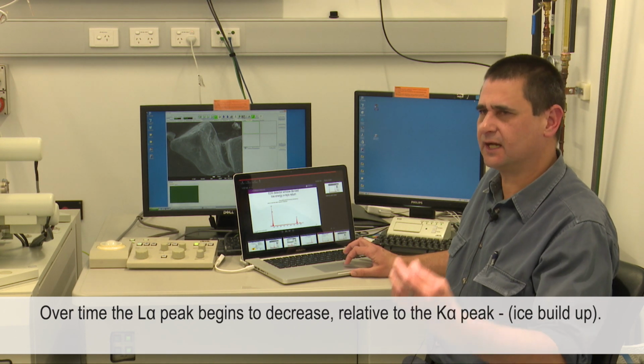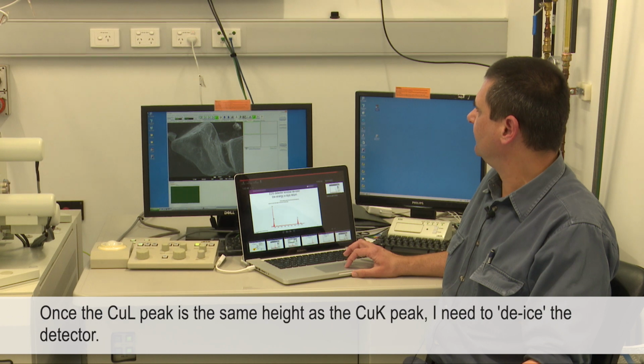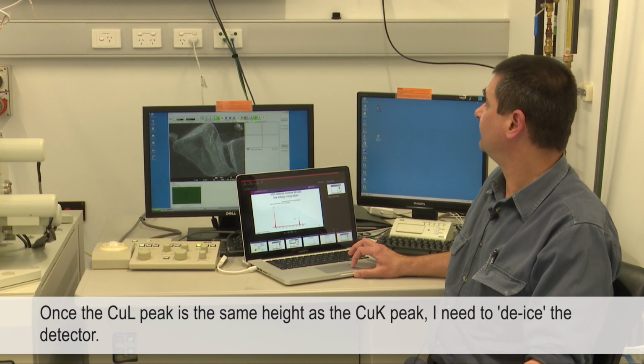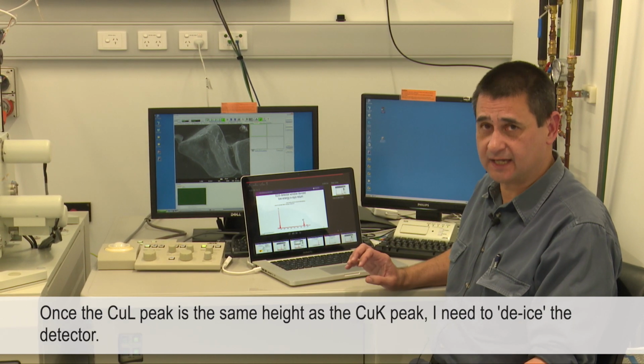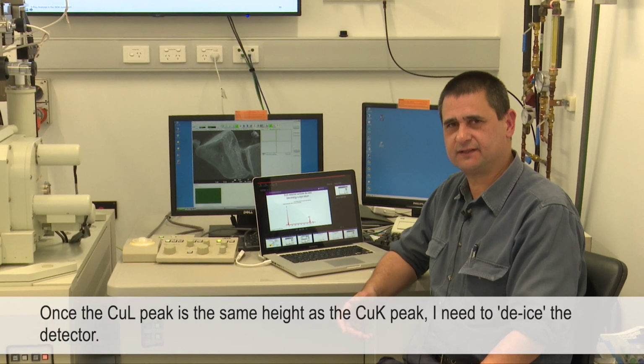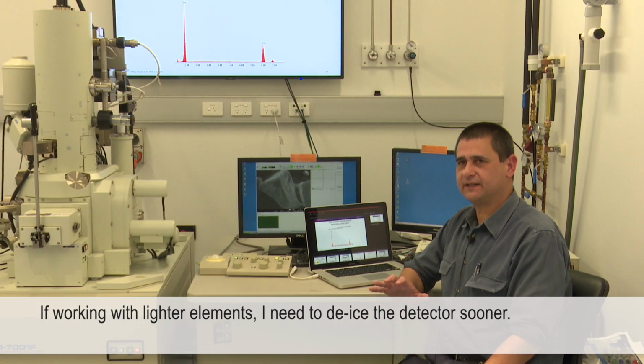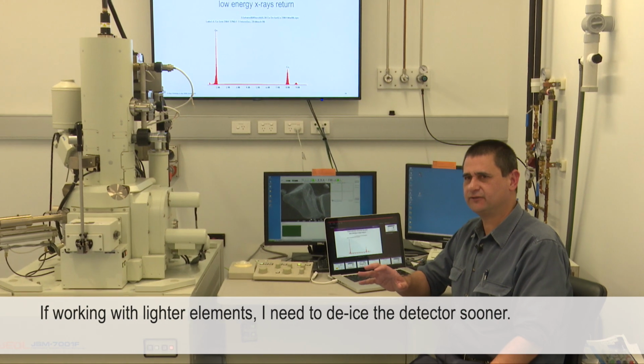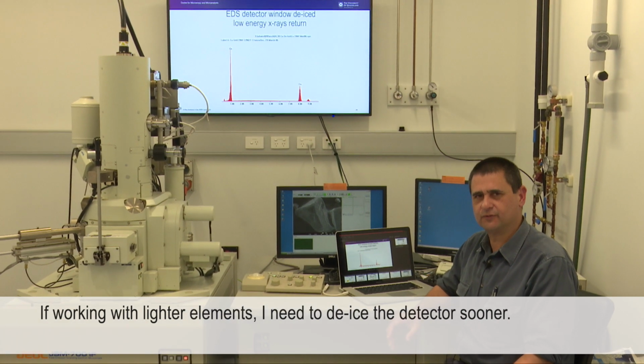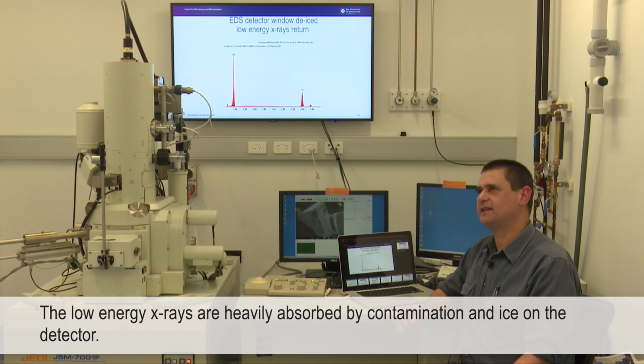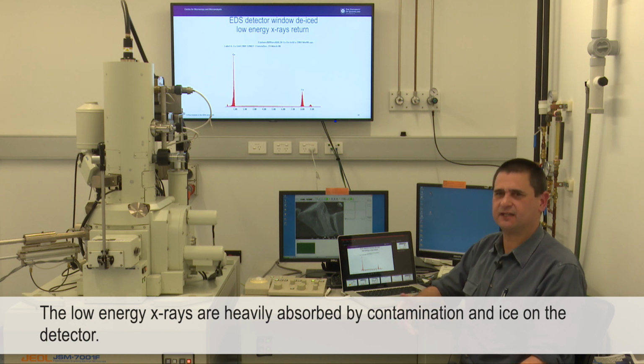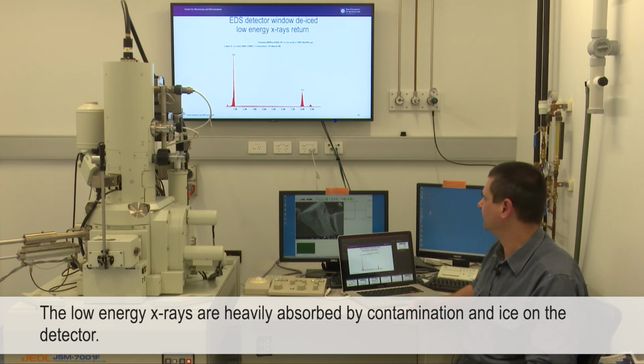That's ice building up. And my general rule of thumb is, once the copper L peak is the same height as the copper K peak, I need to de-ice my detector. If I'm doing a lot of light element work, boron, carbon, nitrogen, then I'll de-ice it a lot sooner than that. It's the low energy X-rays that are most heavily absorbed by contamination and ice on the detector.